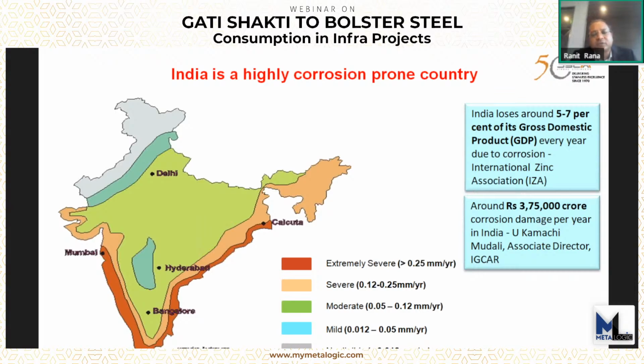So for India, from this map, it is quite clear that 90 to 95% of the country falls under the corrosion region. And this has also been supported by the International Zinc Association, who mention that India loses around 5 to 7% of its gross domestic product every year on account of corrosion. And as per Professor Kamachi Mudali, the Associate Director of Indira Gandhi Center for Atomic Research, around 3,75,000 crores of rupees get expended on account of corrosion damage in India. Therefore, corrosion is a major menace in this country.